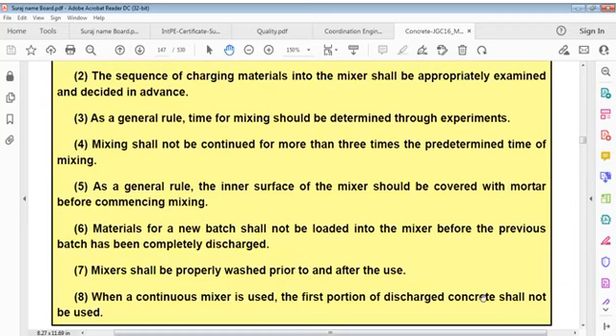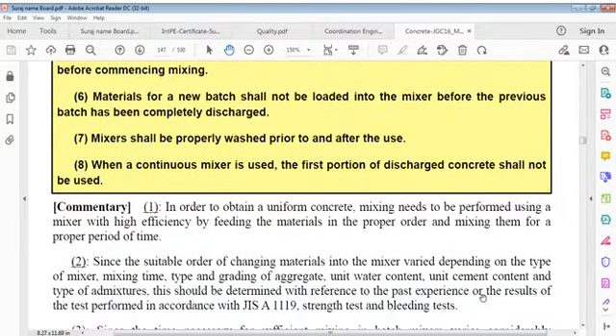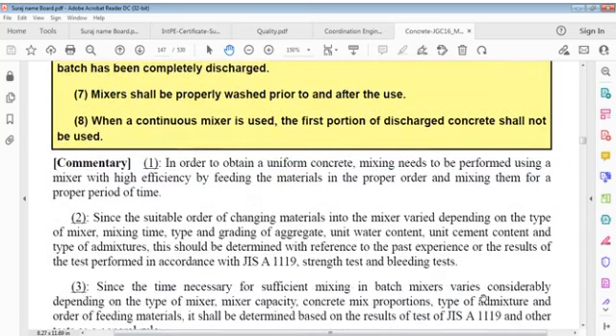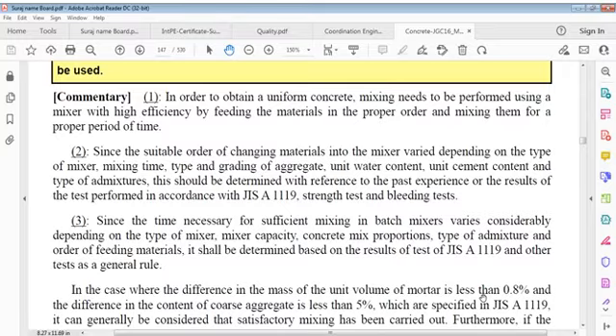As general rule, inner surface of mixer should be covered with mortar before commencing mixing. Materials for a new batch shall not be loaded into mixer before previous batch has been completely discharged. Mixers shall be properly washed prior to and after use. When a continuous mixer is used, first portion of discharged concrete shall not be used. In order to obtain a uniform concrete, mixing requires using a mixer with high efficiency, feeding materials in proper order and mixing them for a proper period of time.